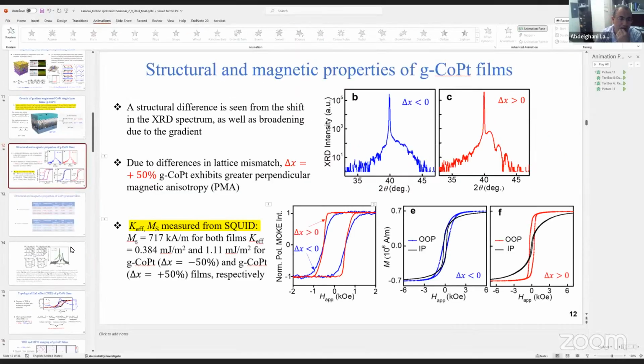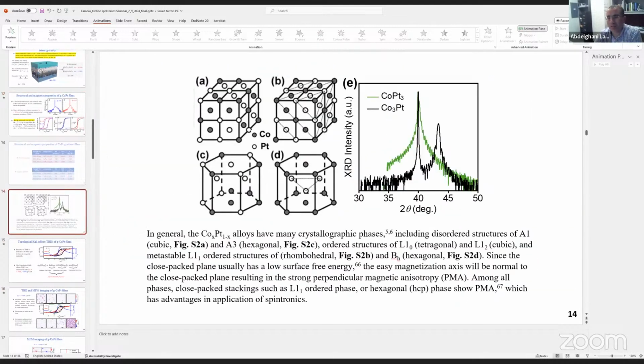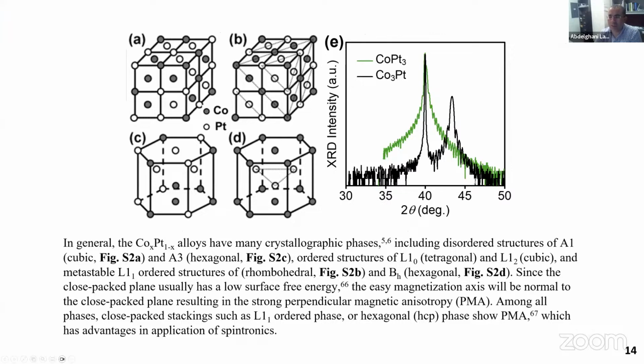In principle, they were zooming in on this peak. But depending on whether you go from cobalt platinum 3 or cobalt 3 platinum, you can create different orders, whether cubic, tetragonal, or hexagonal, this type of order structure, L10. So the fact that you create different order based on the composition will also change the magnetic properties.